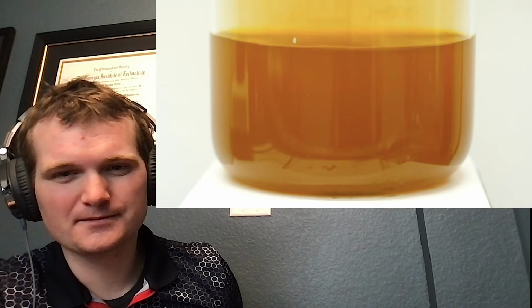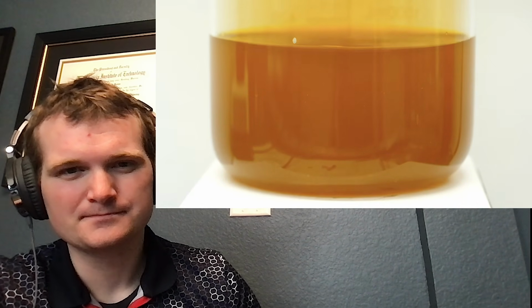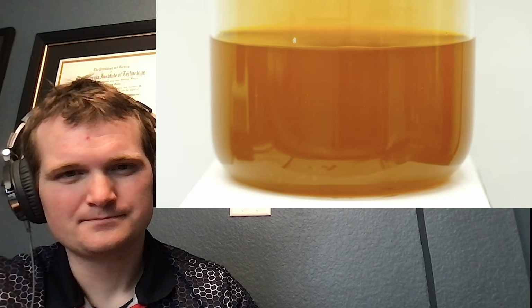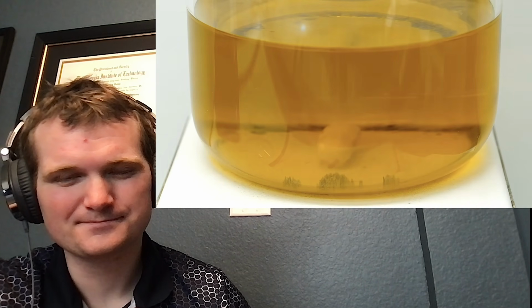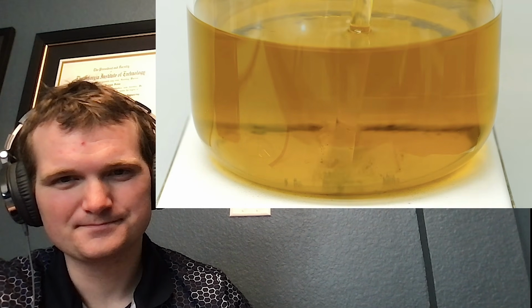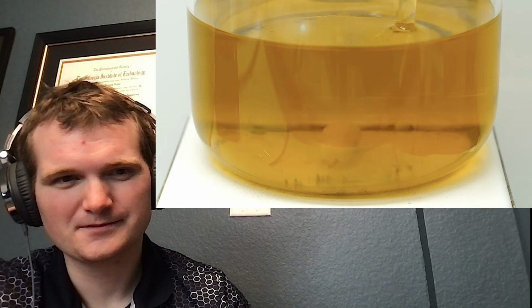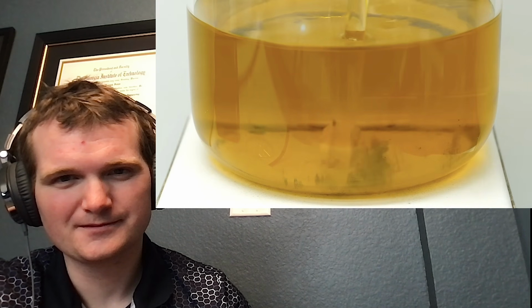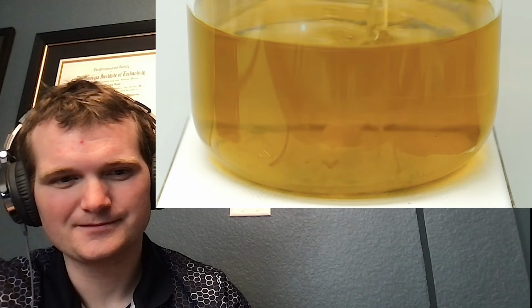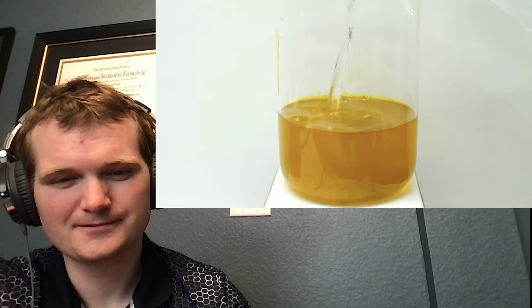I kept adding nitric acid until it pretty much looked like all the gold was gone, and then I left it overnight. The next day, I still had some solid stuff at the bottom, but it wasn't gold. It was all just silver chloride, because apparently there was still some silver left in the gold. So moving on, I diluted